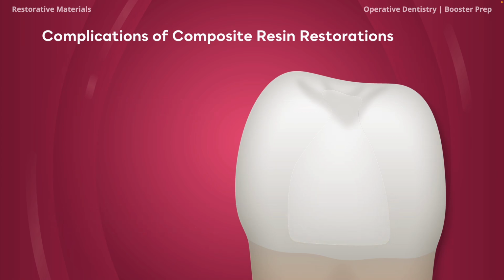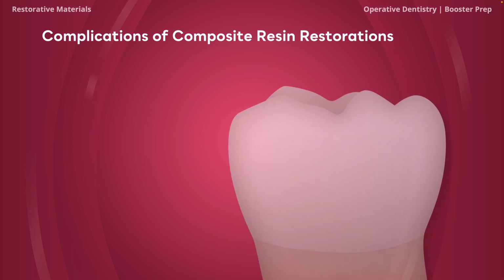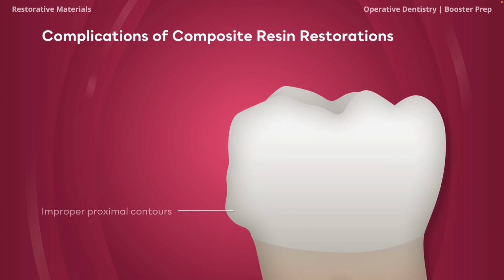Alright, the last complication I want to talk about can't actually be seen from this angle. So let's turn our molar around so that we can talk about improper proximal contours. This is a complication that happens when we don't spend the time to make sure our matrix system is adequately placed. This can result in over-contoured or under-contoured restorations, which can then cause recession and sensitivity. Unfortunately, you'll have to redo the restoration in some cases, depending on the size of the defect.